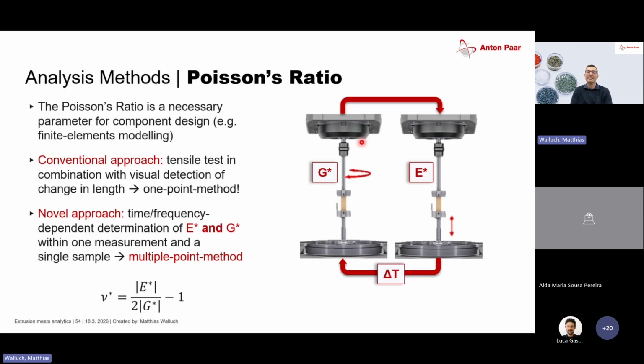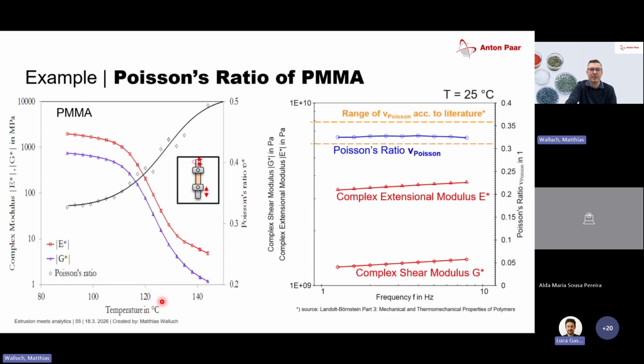And what we can get then is a nice thing, the Poisson's ratio, because G prime or G star and E star are correlated or are connected with each other via the Poisson's ratio. And since you don't need to change the sample, you don't need to touch it anymore, you can directly calculate the Poisson's ratio based on your measurements. As you can see here in red, these are the extensional measurements. So E values are always higher, G values are always lower. And if we correlate them via this equation, we can then calculate the Poisson's ratio dependent on frequency or even on temperature.